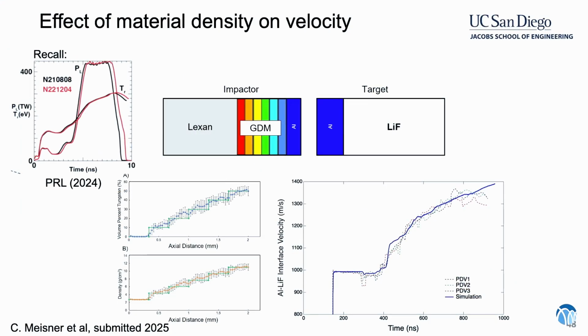Okay. Another way that you can get high pressures is by choosing different materials, like I was talking about before. Going back to this data, here's power on this axis, temperature on this axis, and here's time on this axis. What you might notice is that when the power of the laser was started, it's not all added at once. The peak power is not delivered immediately. Instead, it's ramped. And the reason it's ramped is that to get the highest pressure and the highest temperatures, it needs to be done judiciously. And one way that one can do that is by changing material densities.